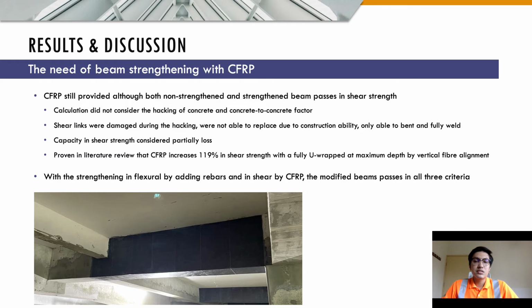The reason is that the calculation did not consider the hacking of concrete and the concrete to concrete factor. Also, the shear links were damaged during the hacking process, and it was not able to be replaced due to construction ability. It is only able to be bent and fully welded. So due to this reason, it is considered that the shear strength of the beam is partially lost. Hence, a beam strengthening approach in the shear strength is required.